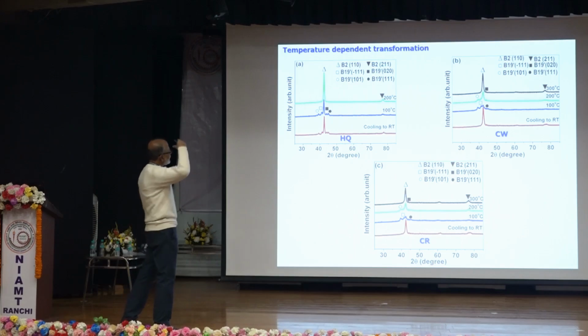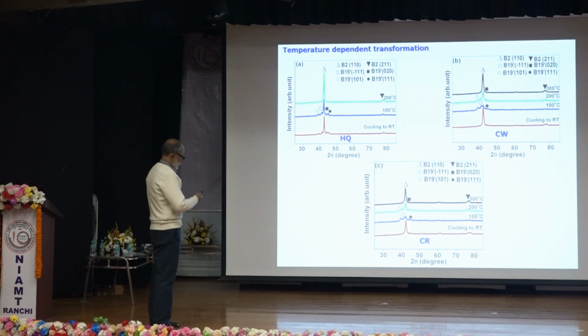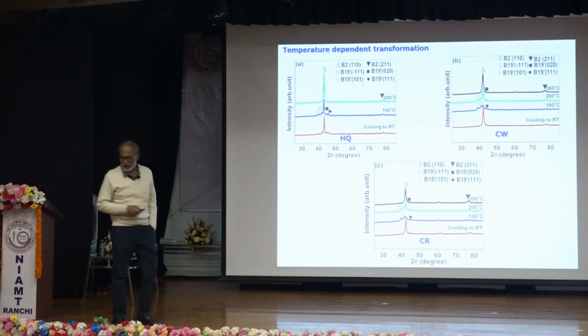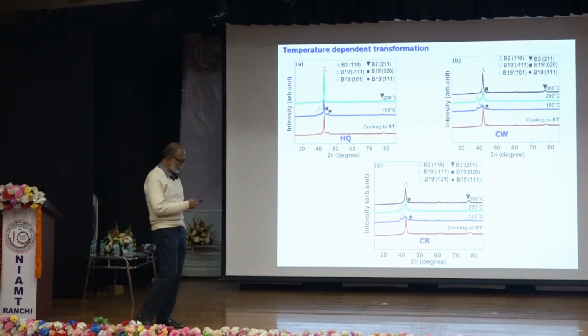And we conducted certain high temperature XRD experiments to assess the stability of martensite. So this is for the sample which is homogenized at 900 degrees centigrade and quenched to ice water. We find single phase austenite we obtain only at 200 degrees centigrade, although the martensitic start temperature is 63. We know the constraint of martensitic transformation by strain or something, we call it stabilization. But here austenite is also constrained. Martensite to austenite transformation is also constrained. So that's how we determine the suitable temperature of aging in the austenitic region, and we had to go beyond 300.